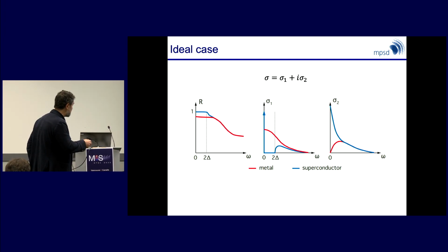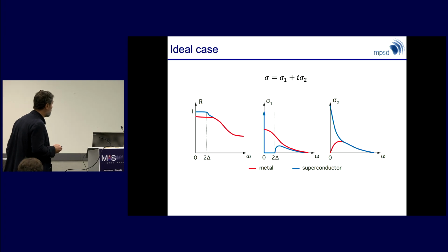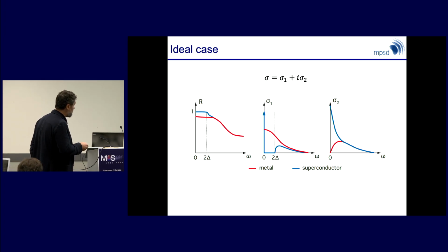exhibits a gap and has a pole at 0 frequency that tells you about the density of Cooper pairs. And if you measure at finite frequency, although you can't see the presence of this pole, you can tell that it's there because what you have is a divergent imaginary part of the conductivity, which has to do with the fact that real and imaginary part are connected by Kramers-Kronig.